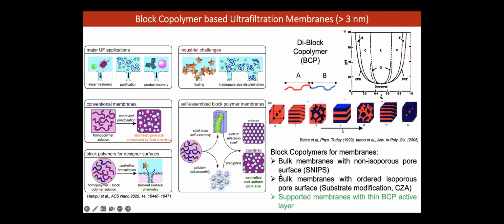A macroporous support layer, but the active layer does all the work. And block polymers have been used by this technique called SNIPS to make what's called non-isoporous surfaces or membranes. Non-isoporous means it's not a single size, there's a distribution. But our goal was to work on these isoporous membranes, which is the true property of block polymers we want to exploit.